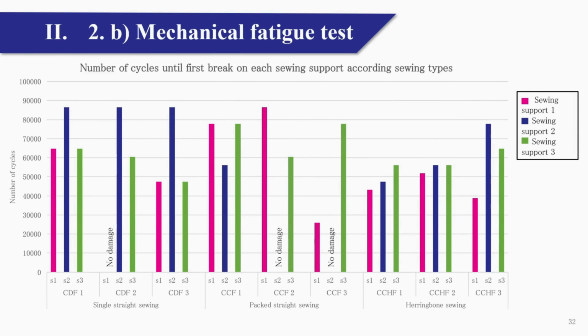The models with packed straight sewing and those with single straight sewing show similar results. After 20 hours of stress, 2 of the 3 models with single straight sewing show all of their sewing supports broken, and 2 of the 3 models with packed straight sewing show 2 broken sewing supports. However, the first alteration appears on average after 10 hours of stress for packed sewing and after 12 hours for the single straight sewing.